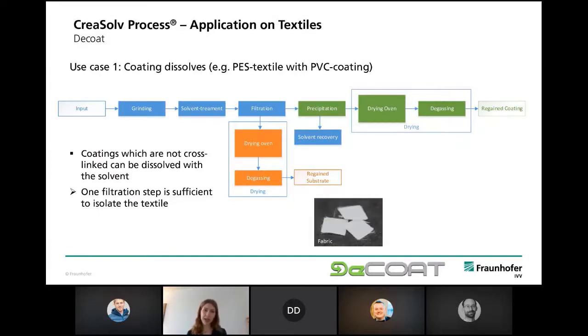Yes, the use case number one is we have a textile, which, for example, is coated with a PVC coating. The PVC is thermoplastic, and so we can dissolve it from the fabric. And here, the fabric can be removed from the solvent by just one filtration step. We will have the textile then, which is, of course, wet afterwards, so we have to make a drying step. And in a degassing step during the regranulation, we can then remove the final residues of the solvent, and we have the regained substrate. The coating also can be removed, if this is what you want, from the solution again. So this could also be regained if this is aimed for.